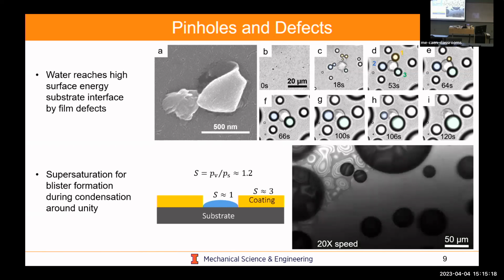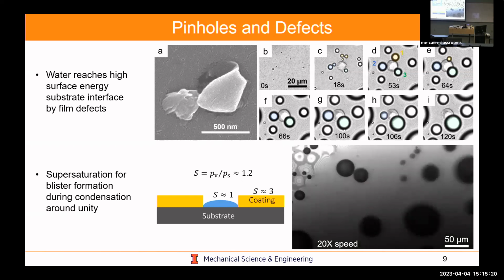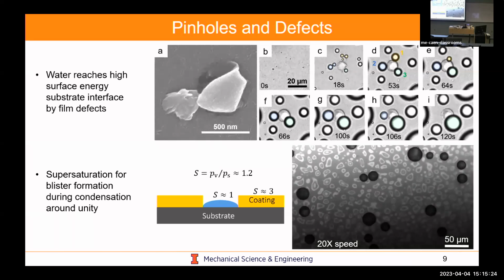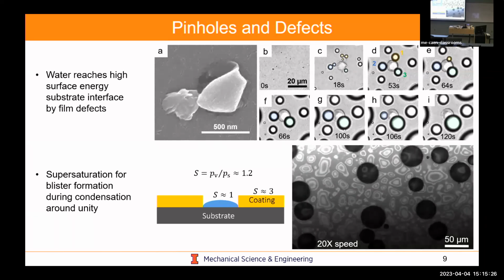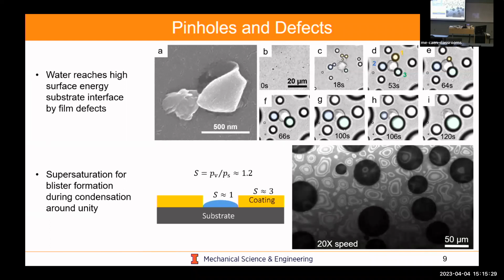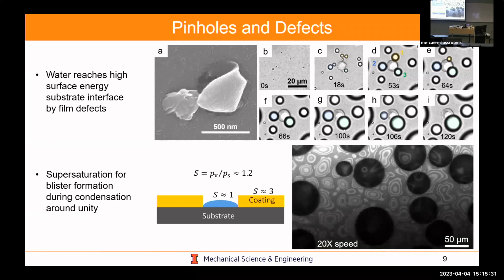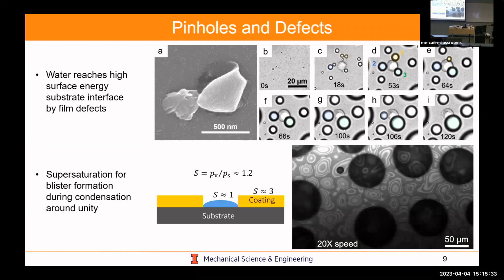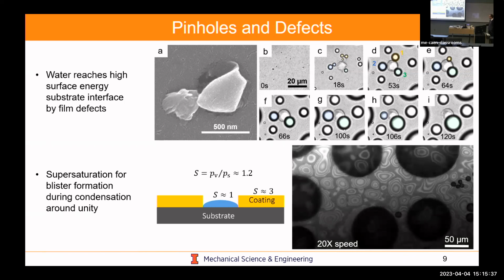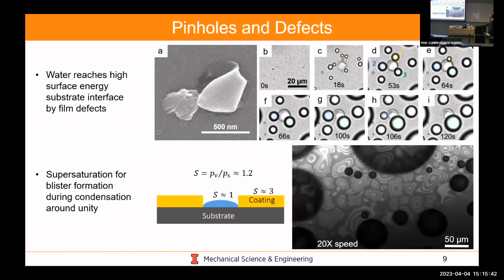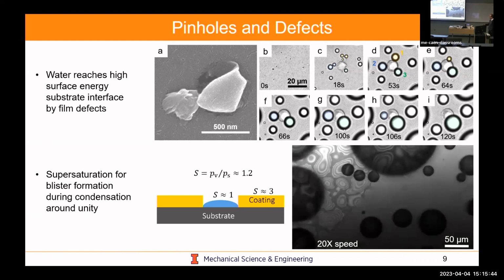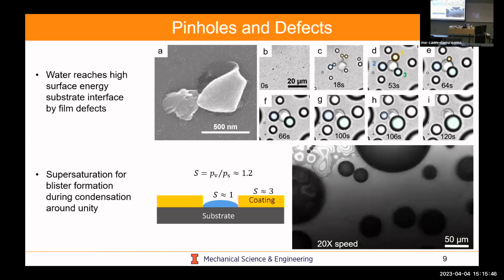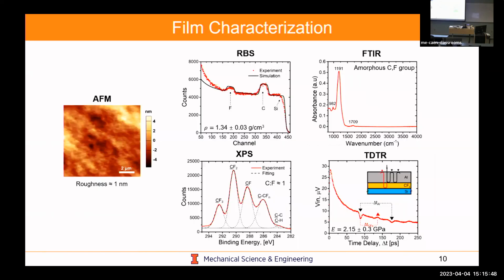You might ask, well, what's the preferential mechanism of why one goes into the other? It's Laplace pressure, so you have higher curvature. This droplet has higher pressure than the droplet in here. So you actually have a driving potential to have liquid move from one to the other. And so this was a first indication of the fact that these blisters are very important. The way they start typically is with some sort of defect, and how can we now better understand how this delamination process occurs, and can we actually use something like mechanics to help us in that vein.